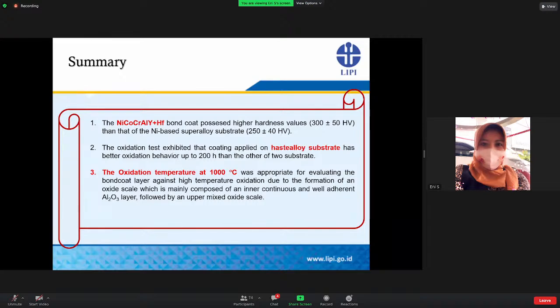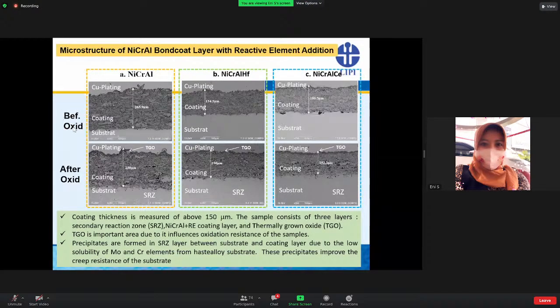The cross-sectional structure before and after oxidation of the nickel, chromium, aluminum bond coat with the reactive element is shown in these figures. It shows that the coating system thickness measures about 150 micrometers. The improvement of the structure in the bond coat layer from the previous research could be recognized as denser, less porous, and relatively smooth compared with the previous HVOF samples.